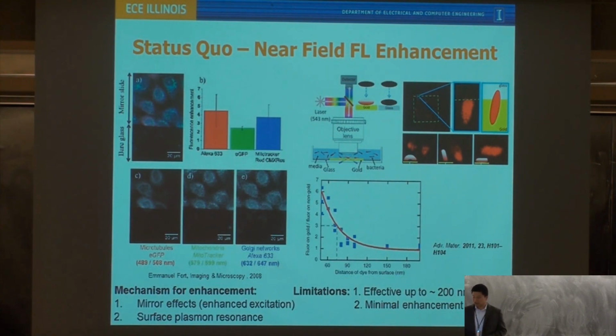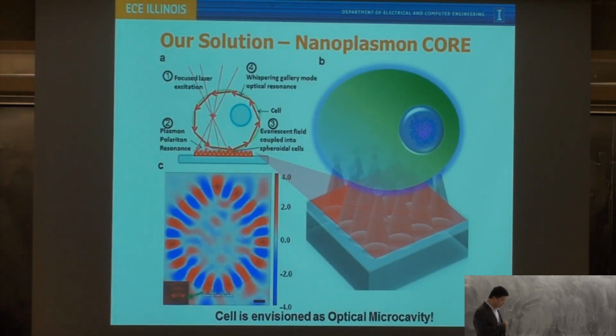Even when you use an actual nanostructure there, you probably get a little more enhancement for cell imaging, but you still have a limitation: you see the enhancement only on the surface, because this is pretty much a near-field effect. You have your electromagnetic field enhancement basically focused on the surface. If you move away from the surface, your enhancement factor drops significantly, exponentially. But here we want to propose a hypothesis that we can do better three-dimensional imaging, particularly for spheroidal cells. Of course, when a cell really spreads out like a very flat sheet, this will not work. In that case, you're going to use surface-enhanced fluorescence. But this is our hypothesis based on our observations.